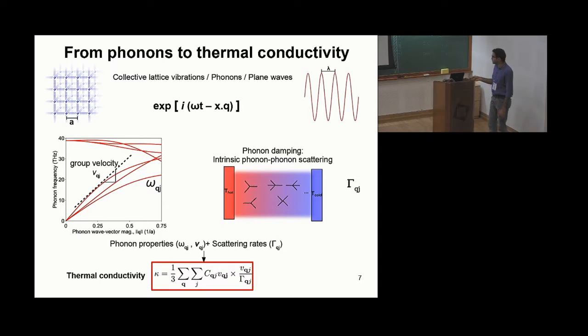This is an expression directly taken from kinetic theory, where the thermal conductivity of any material is written as a sum over all phonon modes in the crystal structure. Q is an index for the wave vector, and J is just the polarization, which marks J equals 1 as this one, J equals 2 as this one, and so on. So you have 6 different modes in this case.